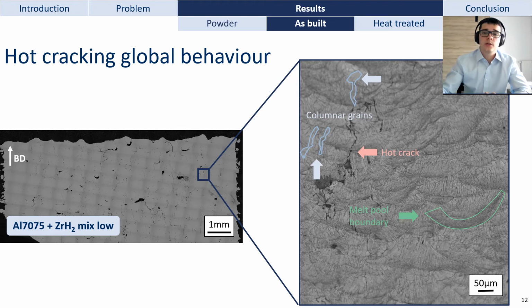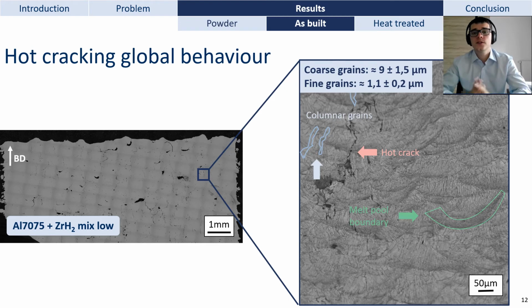But let us look at its microstructure to understand this phenomenon. By looking at the optical micrograph, we can see some big columnar grains that remain and that cross several melt pools. And you can also see the grain refinement effect of the zirconium at the melt pool boundaries. So we can distinguish a bimodal grain structure composed of fine grains located at the melt pool boundaries and of coarse grains inside the melt pools. If we quantify the size of these grains, we can approximate at 9 microns the coarse ones and at 1.1 microns the fine ones.